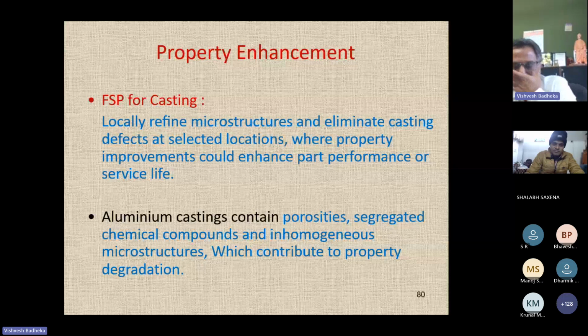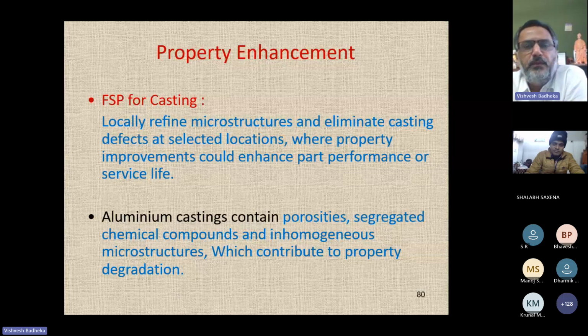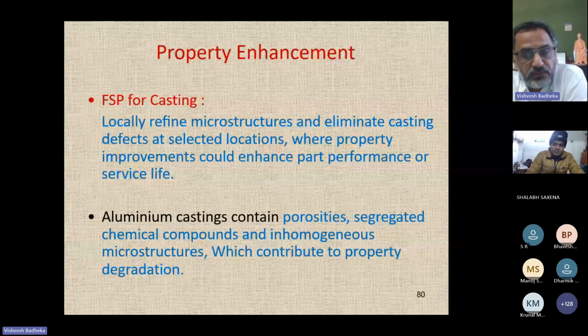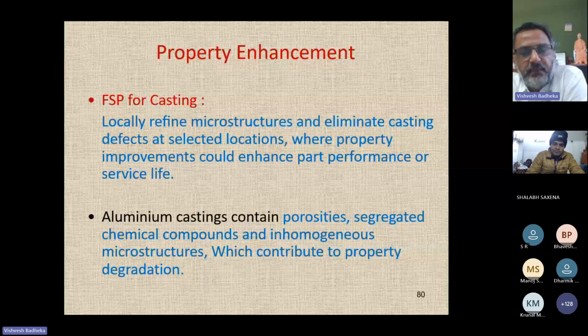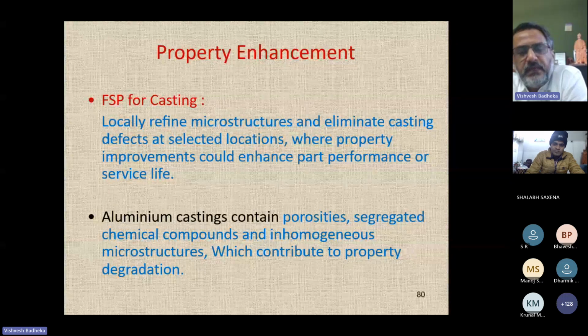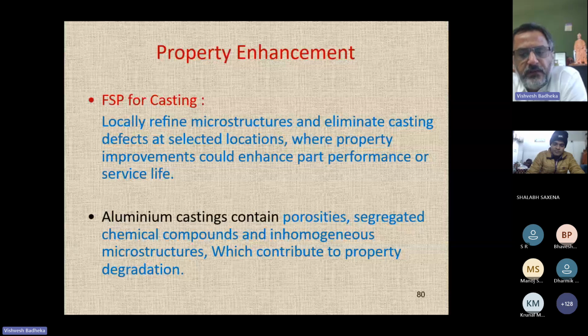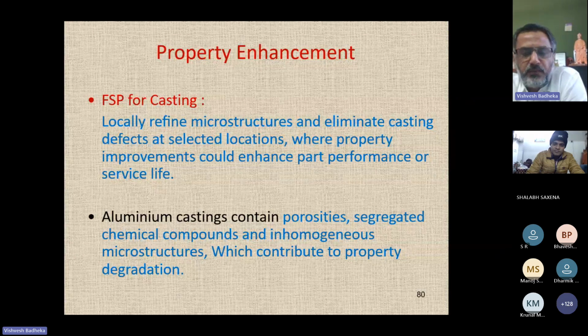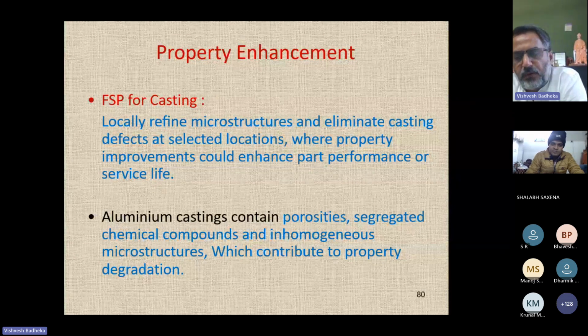So as I mentioned, friction stir processing has been reported for castings too, because if you look at aluminum castings, they contain a lot of porosities and segregations, right? Segregation is what? The non-uniform distribution of chemical compounds. You have an inhomogeneous microstructure, right? So you will get poor properties.